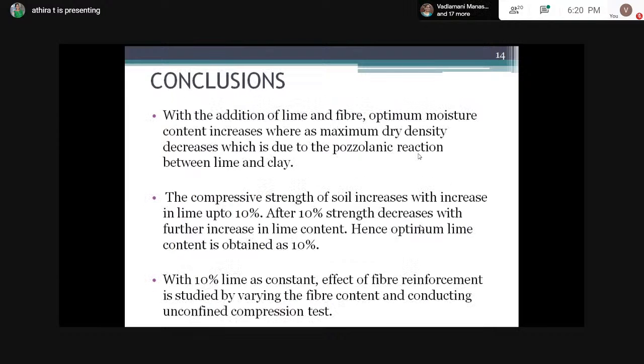Now going on to the conclusions, with the addition of lime and fiber, optimum moisture content increases whereas maximum dry density decreases, which is due to the pozzolanic reaction between lime and clay. The compressive strength of soil increases with increase in lime up to 10%. After 10%, strength decreases with further increase in lime content. Hence, optimum lime content is obtained as 10%.